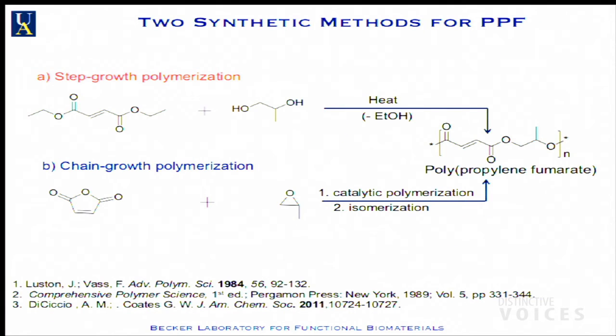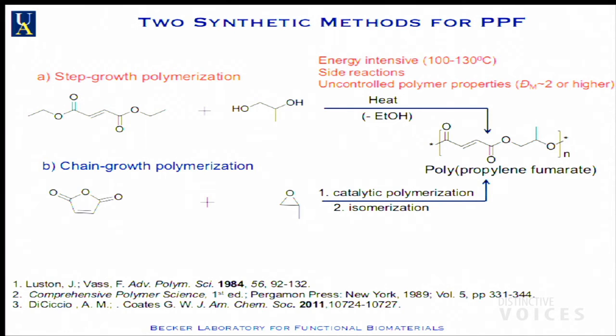Now, how they had been making it was a process called step growth polymerization, which is how polyurethanes are made, foams, okay? It's fantastic chemistry for very high molecular weight material. But beyond 3,000 Daltons, which is about 14 subunits of this material, it transitions from that honey material, which is very useful, to a solid, which is not useful for printing.